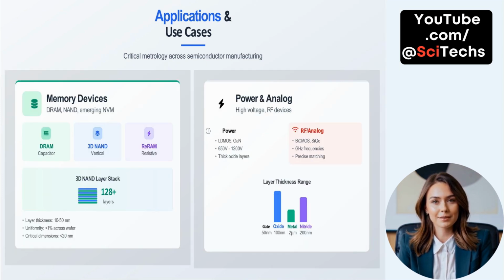Applications and use cases. Film metrology is essential in supporting memory and analog device performance. In memory devices, metrology ensures tight process control across dynamic random access memory, 3D NAND devices, and emerging non-volatile memory such as ReRAM. Dynamic random access memory capacitors require uniform dielectric thickness for reliable charge storage. In 3D NAND devices, vertical integration introduces added complexity, with over 128 layers now standard in modern devices. Each layer ranges from 10 to 50 nanometers in thickness, and maintaining 1% uniformity across the wafer is critical. For ReRAM, resistance-based switching depends on precise control of ultra-thin layers and critical dimensions below 20 nanometers.